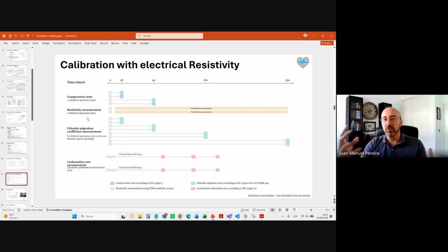So this continuous information, in my experience, gives you a lot of new perspectives. When we see 1 point here and 1 point here in the chart, like 28 days, 90 days, in our mind this is a straight line. But you see how these things evolve over time. It's not straight, or maybe it's going up, or maybe you get surprised that after a year or 2, things that you didn't expect to keep evolving, they do keep evolving.